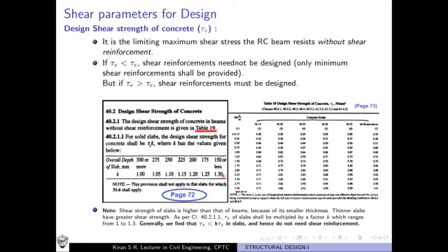So as you increase the thickness of the slab, the value of K is decreasing, or in other terms, as the depth of the slab is decreasing, the K value is increasing, which means that the capacity of the slab to resist shear stress is more if the thickness of the slab is very low. So thinner slabs will have more shear resistance than thicker slabs. That is exactly the reason why we don't require shear reinforcement for slabs. We design shear reinforcement only for beams, and for slabs we generally don't design for shear reinforcement.